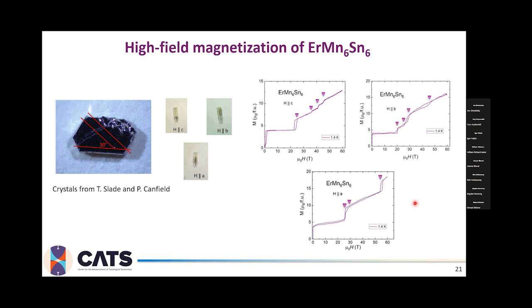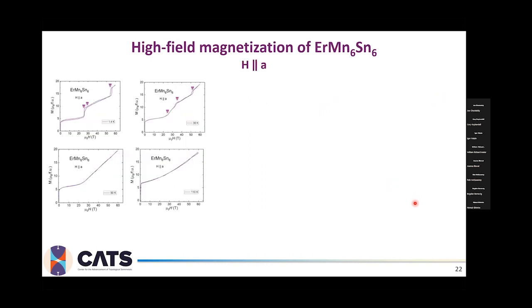So I would like to go quickly through each of these directions. What we can see over here is that when we increase the temperature with the magnetic field along the A direction, these two transitions are actually getting closer to each other as we go towards higher temperatures. At the very high temperatures, like 50 and 100 K, there is only one transition, which is smoothly getting smeared out. The interesting part is that at low field, when we are above that transition around 91 Kelvin, we can see a hysteresis showing up at the low field, which becomes bigger at higher